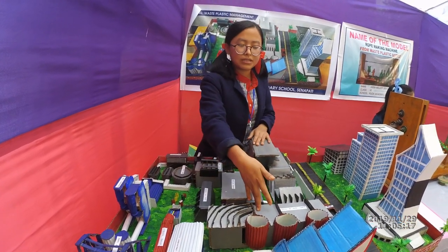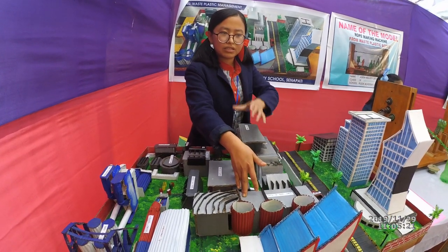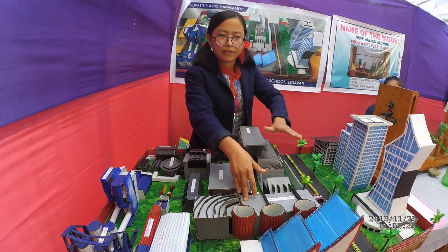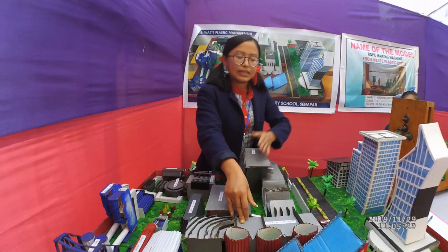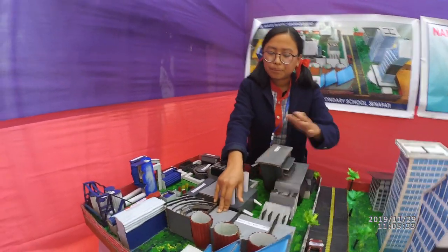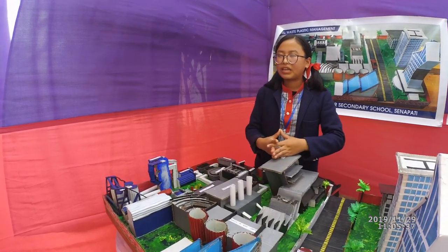And then plastic to road construction. The plastic is shredded and mixed with hot stone at an average temperature between 150 to 170 degrees Celsius. And then it is used as a binder in the plastic to road construction. And all these techniques are summed up together so that